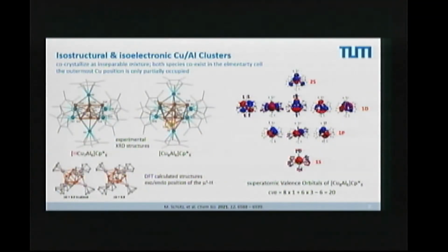What you see here are the cluster valence electron orbitals of these two clusters, and they have a very nice symmetry. It's almost a spherical packing of the copper and the aluminum, and what you get is a 1s symmetry kind of low-lying cluster valence electron orbital. You have p-type, you have d-type, and you have again s-type. Now you see here the one principal quantum number, and if a student in the first year of chemistry would say in the hydrogen atom there is 1s, 1p, 1d, you would get 0 points for this answer.